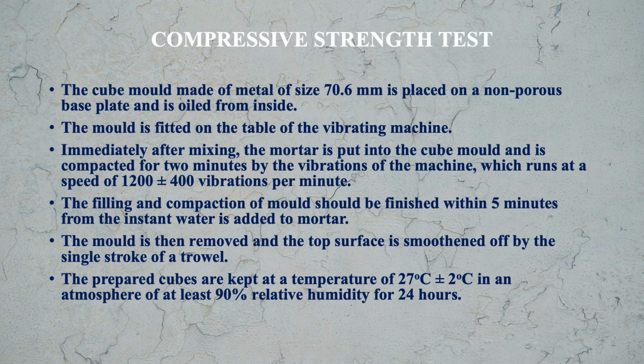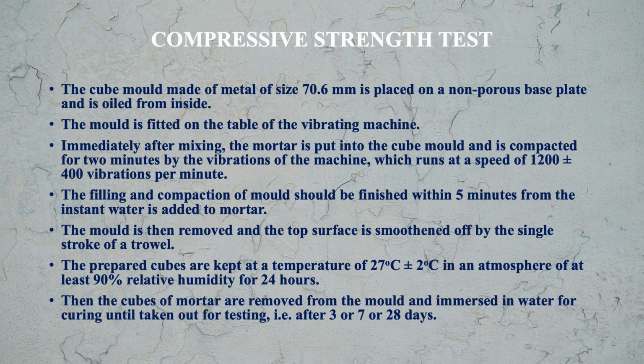in an atmosphere of at least 90% relative humidity for 24 hours. Then the cubes of mortar are removed from the mold and immersed in water for curing until taken out for testing, after 3 days, 7 days or 28 days, when you want to test the cube.